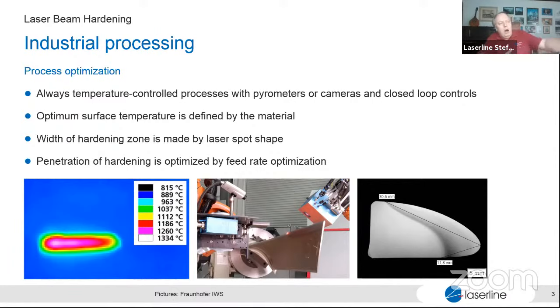And we need a local hardening at these blades for avoiding droplet erosion. And this is just an example of what the laser can do: very local heat treatment on these parts. We need the hardness just at the tip, and we don't need an elevated hardness in the very ductile root of this blade. And what we need for doing laser hardening for most parts is a very well adapted shape of the beam. We don't necessarily have a round spot for laser hardening.